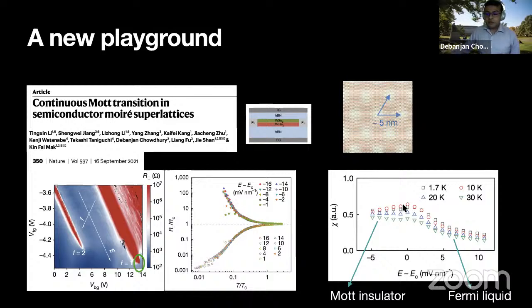Now, this is kind of bizarre if you think about it, because at low temperature in the Fermi liquid, the spin susceptibility really comes from the electronic Fermi surface. So all of these low energy excitations near the Fermi surface contribute to an almost temperature independent susceptibility. But when it evolves smoothly into the Mott insulator, what that basically tells you is that the spin excitations in the Mott insulator, they're not gapped. In fact, it sounds like there are a lot of low energy spinful excitations in the insulator, even though you have a well-developed charge gap. Okay, so this is of course interesting, and maybe the experts already know which way I'm going with this as I proceed with the rest of the talk.